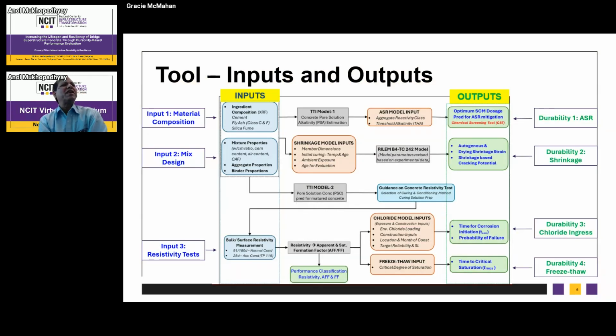This slide is already developed. You don't have to go through it; it gives an idea that in this Excel-based tool, we give input of material composition, mix design information, and resistivity measurement of the concrete mix. The tool uses those inputs and some other intermediate level inputs, and the models are inbuilt, and based on the model and input, it predicts 4 major durability aspects of the concrete. One is the ASR prediction, how much supplementary cementitious material you need to mitigate ASR, and then the amount of autogenous and drying shrinkage and cracking potential of the mix, and then time of corrosion initiation or probability of failure of that mix, and the time to critical saturation as a measure of freeze thaw durability.